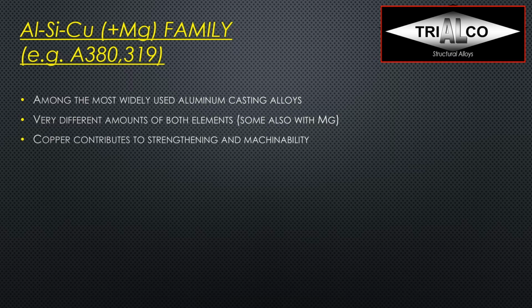Copper contributes here to the strengthening and the machinability. It of course also makes it strong at higher temperatures. That's why we can see those alloys used for a lot of engine castings. Silicon improves the castability and reduces hot shortness. And the aluminum, silicon, copper alloys with less than 5.6% copper are actually heat treatable. Although most A380 castings, of course, are not heat treated because they're die castings.